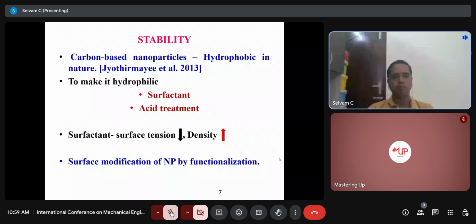So in order to avoid this, we can go for surface modification also. So surface modification of the nanoparticle by functionalization can be done. In that it won't change the surface tension, but the particle that is hydrophobic in nature can be changed into hydrophilic. So directly, hydrophilic nanoparticles we can disperse in the water. That we have done.